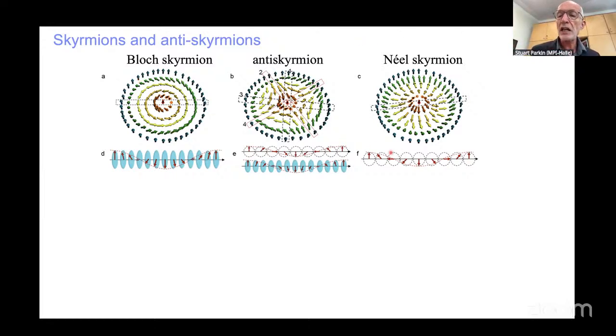On the right-hand side, you can see a Néel skyrmion, same as the Bloch, but here the magnetization rotates from up on the outside to down on the inside by rotating along the domain wall, just like the domain walls in the racetrack I mentioned earlier. And now in this case, in both the Bloch and Néel cases, the domain wall has the same structure all the way around the object. However, it was theoretically predicted that in certain materials with a lower symmetry, depending upon the crystallographic direction, the sign of this Dzyaloshinskii-Moriya exchange would change sign. So in some directions, you would get a Néel wall, shown in this, let's say 3, and in some directions, you get a Bloch wall.